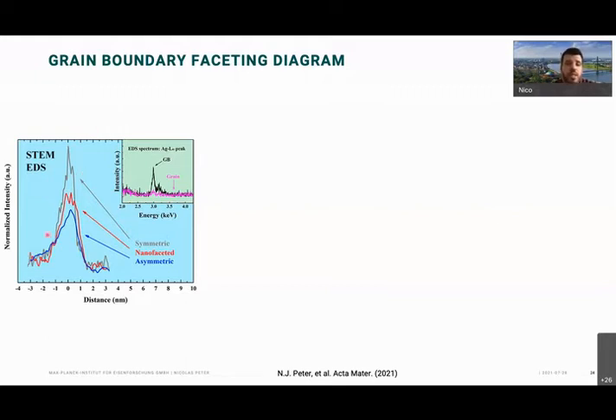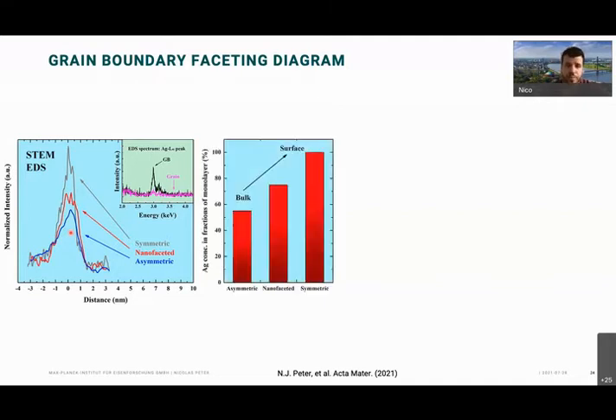So this is now what we did here, and we did this for the symmetric portion at the surface, which is the gray with highest intensity. We did this for the nanofaceted case, and we did this for the asymmetric case. So we plot here only intensities because we did this in zone axis. And if you have an atomically resolved image where you see a nice crystal structure, be very careful about the EDS quantification. That does not really hold too much anymore.